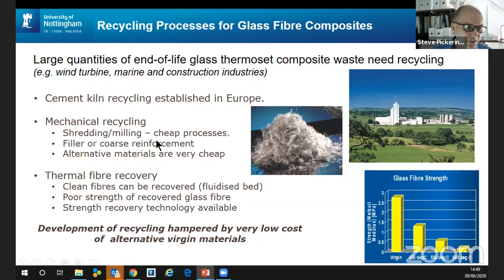Mechanical recycling can be considered, where you would just shred the materials up, and you don't necessarily separate out the polymer from the fibers. If you mill into a very fine powder, you can effectively produce a filler, or if you shred less finely, you can have some reinforcement materials, as you can probably see from this picture here. The problem in reusing these materials back in new composites is that the alternative materials, the virgin fibers and virgin fillers, are very cheap, and so it's difficult to make this work economically.